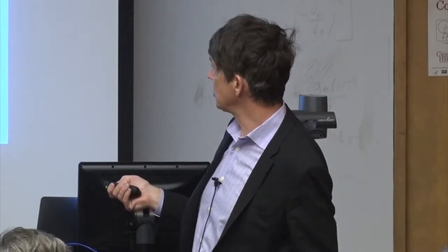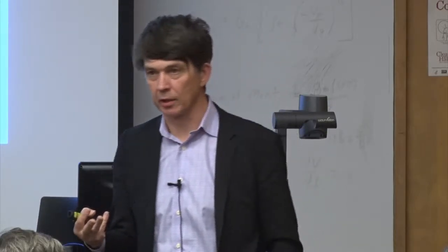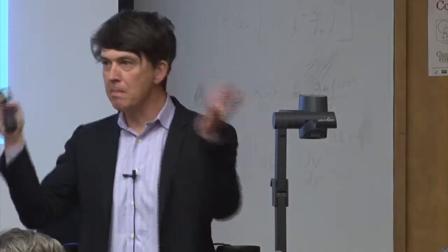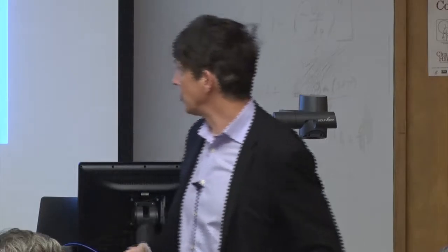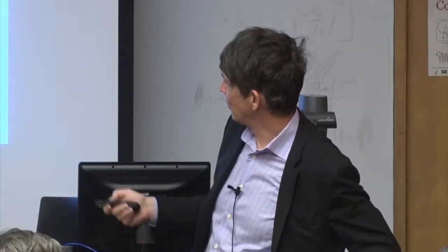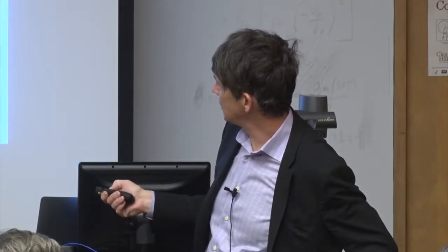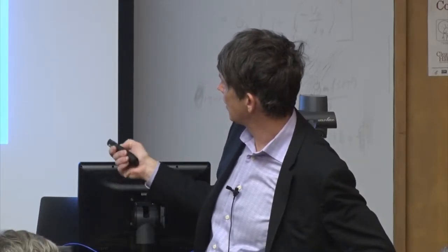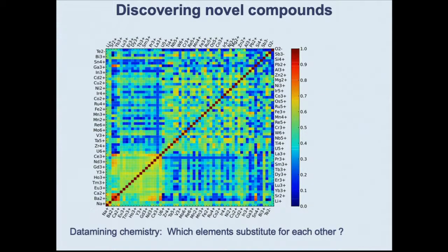And so this is a matrix of essentially most elements against all other elements. This is actually the cations all. And the color scheme is essentially how easily they substitute for each other, retaining crystal structure. So if we have that information, we can take known compounds and make them in another chemistry. That's really what this does. And just for those of you who know your periodic table well and substitutionability, this is, of course, the lanthanides here, right? They have high substitutionability for each other. This here is the column 2 elements, right? Barium, calcium, strontium. This is the transition metals. And so you generally pick up which elements are substitutional for each other. You don't need to have the right answer. You just need good guesses because in the end you do density functional theory on them.